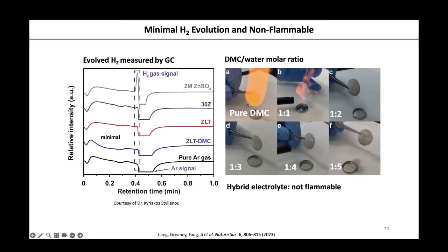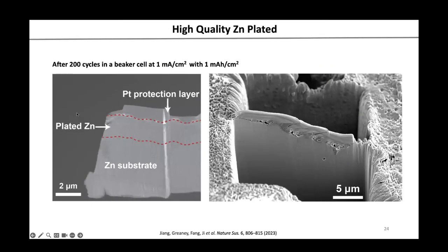So by comparing different electrolytes: DMC is known to be flammable, but it depends on the ratio. If you use pure DMC, of course, it's going to be flammable. If you have 1-to-1 DMC with water in terms of molar ratio, it's going to be flammable too. But if you increase water's ratio, so DMC versus water is 1-to-2, then it's not igniting here. Our electrolyte is right here, where DMC versus water is 1-to-5. So it's very safe.